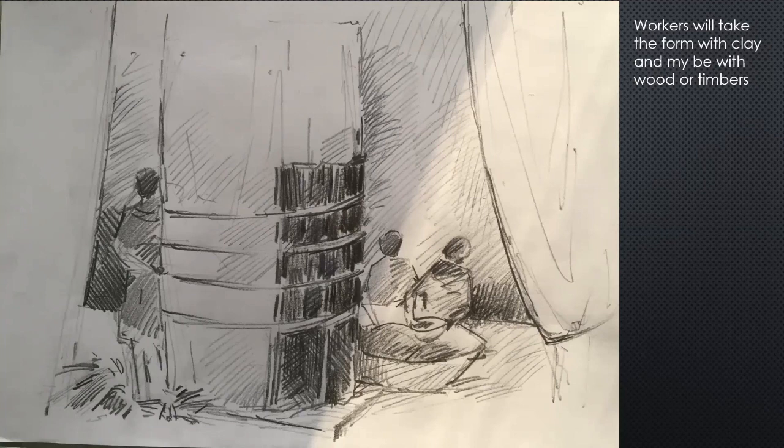In the meantime, the formers in the second hall were busy preparing the wax. Beeswax, which was delivered in huge amounts, had to be treated before it could be used for building the mold. To improve the optical impression, ferrous oxide was worked in, which can be detected in the fragments of the molds that were found. Thus, the surface became blunter, and the plastic effects of details could be assessed more easily.